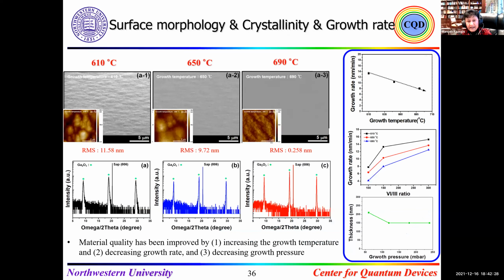So we optimized as a function of temperature - 610, 650, 690 - doing the usual variation as a function of growth temperature, variation as a function of growth rate, and at the same time the V/III ratio.